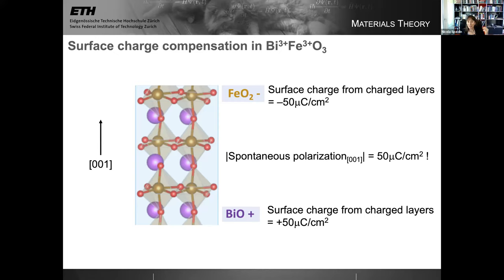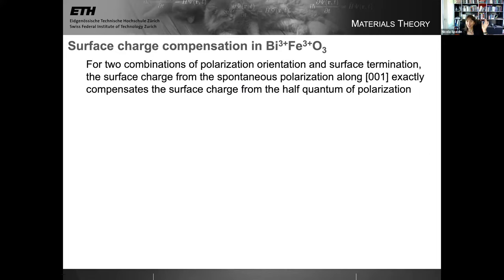So you can immediately see, depending on how the polarization is oriented relative to these surfaces, I can end up with a net surface charge that's either very large or cancels out to zero, right? So I have two combinations of polarization orientation and surface termination for which the surface charge from the spontaneous polarization exactly compensates the surface charge from the charged layers, from this half quantum of polarization.